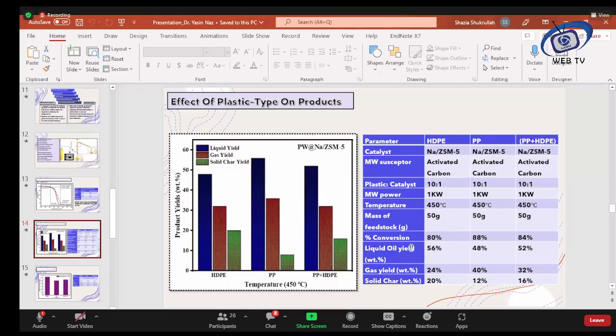80% of HDPE converted into liquid and gases, and the rest, 20%, was the solid product. Similarly, under the same conditions, PP showed 88% change into liquid and gases, and 12% was the residue, which we anticipate would be structured carbon, I mean carbon nanotubes. Later on, we characterize this material to check whether it is char, amorphous carbon, or a structured carbon in the form of carbon nanotubes. Similarly, the mixture of these two plastics produced 84% gas and liquid, and 16% was the residue.